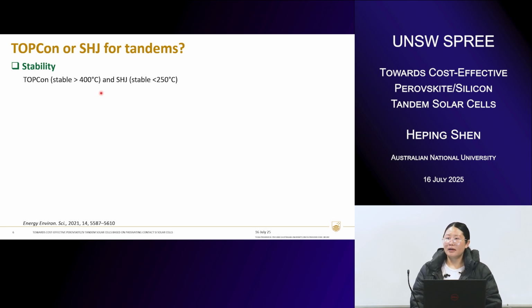That's because, in the first place, for developing perovskite silicon tandems, there are various processes in the perovskite fabrication that may involve high temperature. For example, the highly efficient functional layers like charge transport layers, nickel oxide or titanium oxide, or the very thermally stable perovskite compositions like fully inorganic perovskite, which requires more than 300 degree post-treatment to allow a phase-stable perovskite. So for the perovskite silicon tandem, that's very important. And at a big picture level, it's also very important for developing silicon-based tandems with other potential tandem technologies like thin film, which also usually involves high temperature processes. So we think that's very important and gives TOPCon another advantage compared to silicon heterojunction from the stability point of view.